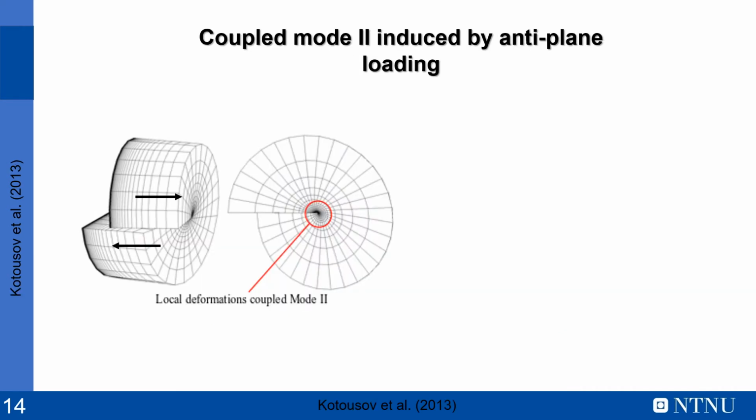The dual coupled mode to mode 3 is the mode 2 induced by antiplane loading. Here the audience can see a scheme of a finite element model loaded by out-of-plane shear stress, where local deformations similar to mode 2 are present.